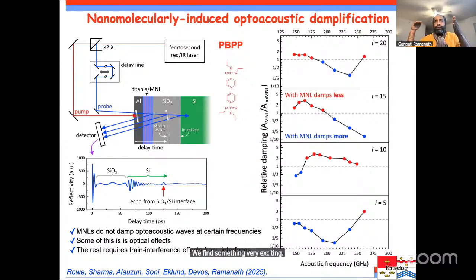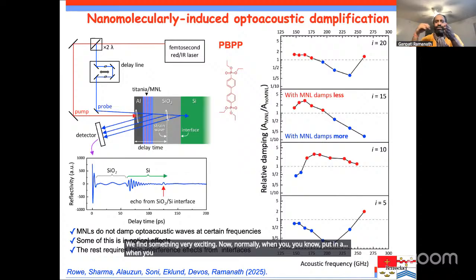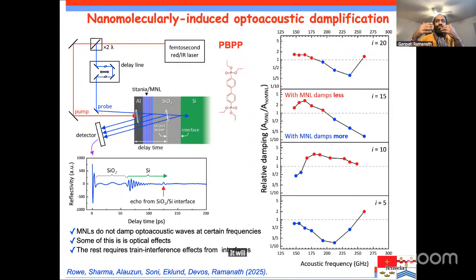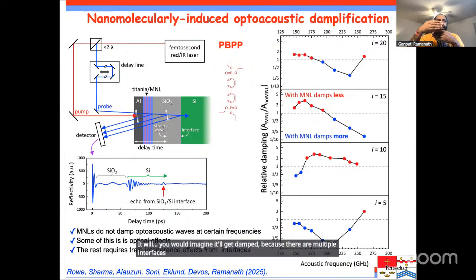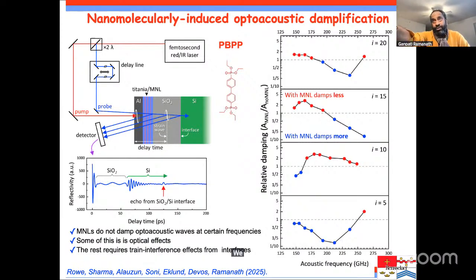Now, normally, when you put in a pulse, let's say of a mechanical wave, you would imagine it'll get damped because there are multiple interfaces which has these molecular layers. But then, when we put these multiple layers, we find, as you see in the graph on the right side, at certain frequencies it damps, which is shown by blue. At certain other frequencies, the signal is actually amplified.